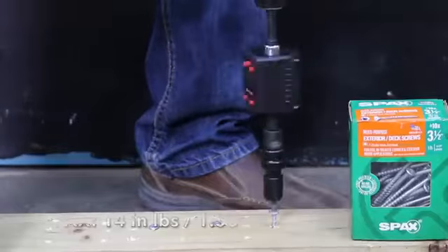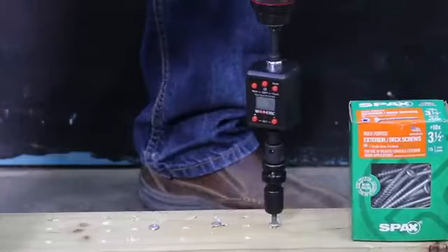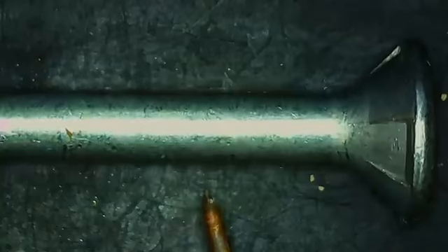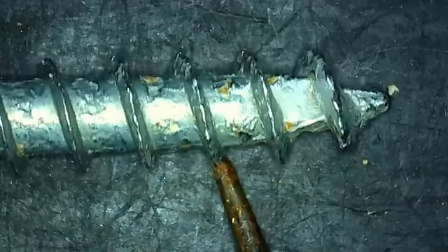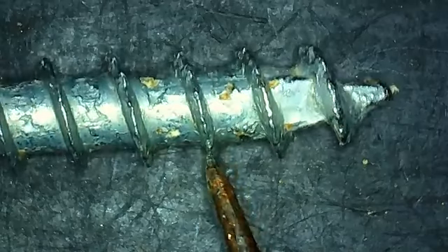14 inch-pounds on the third screw, so 18 inch-pounds on average, the most yet of all the brands. The color of the SPAX coating makes it very difficult to find the exposed metal areas, but the SPAX seems to be in great shape. And the SPAX held up really well drilling through the oak with very little metal exposure on the outer threads.